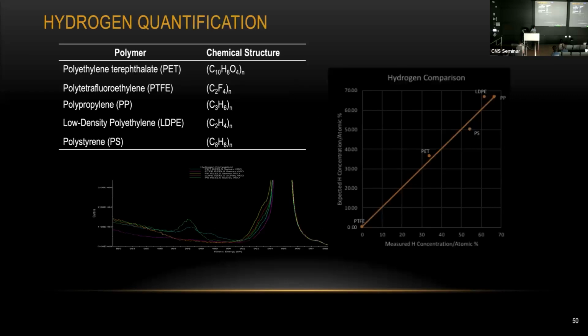Here I just give some data from REELS to show you how we can try to quantify hydrogen. That's the raw data from the measurement. This is a measurement on a bunch of different polymers: PET, PTFE, which is Teflon, polystyrene, and so on and so forth. And we're actually looking for this shoulder peak right here. Different materials with different amounts of hydrogen will have a different shoulder peak.